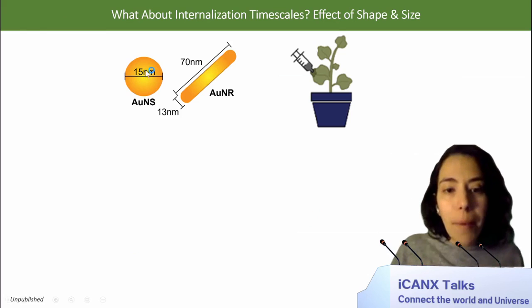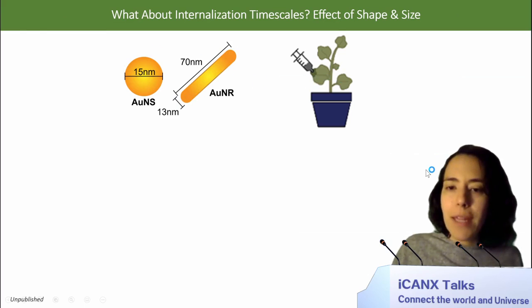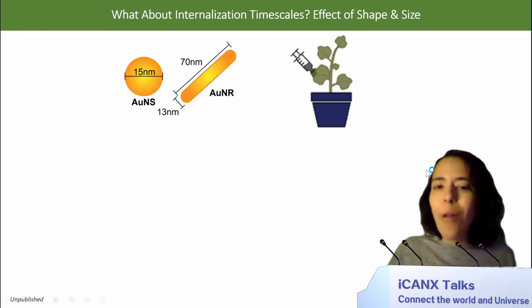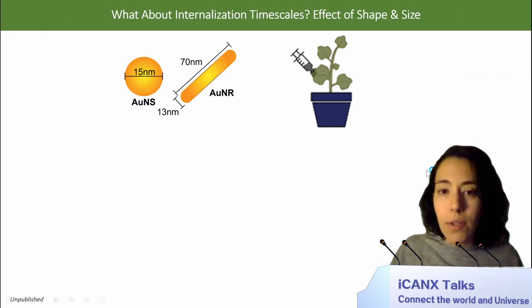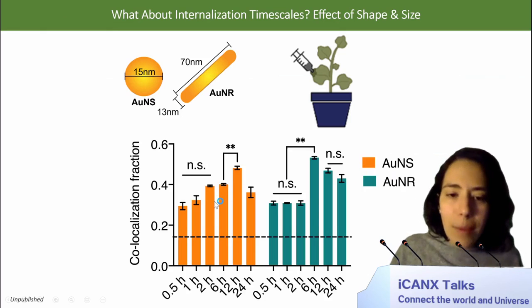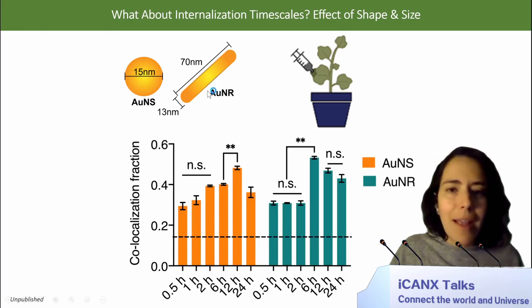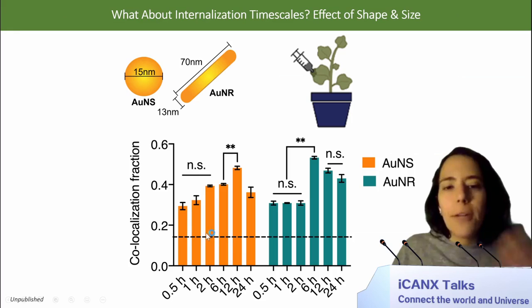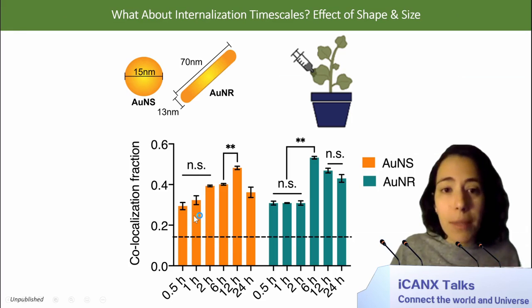So here I'm comparing gold nanoparticles, specifically 15 nanometer versus 13 nanometer gold nanospheres and rods, where the main difference here is again in the aspect ratio of the gold nanorod. Labeling these with Psi3, introducing them into plant tissues, and now asking the question, how long does it take for these particles to internalize? What's interesting about these results is that despite, again, the aspect ratio being the main difference between these two particles, we see very different kinetics of internalization into plant cell cytosol.